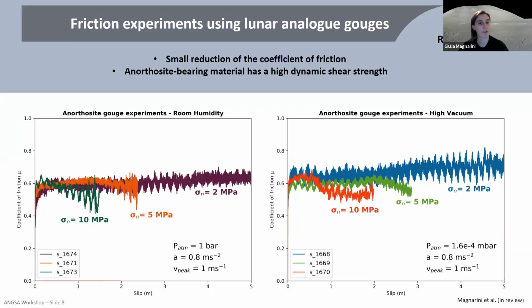And these are our results. So left-hand side, room humidity result, right-hand side, high vacuum result. And on the vertical axis, we have the coefficient of friction. And what we see here is that we have a small reduction of the coefficient of friction, which is actually happening only at the higher normal stresses applied. And so we conclude that the anorthosite-bearing material has a high dynamic shear strength.